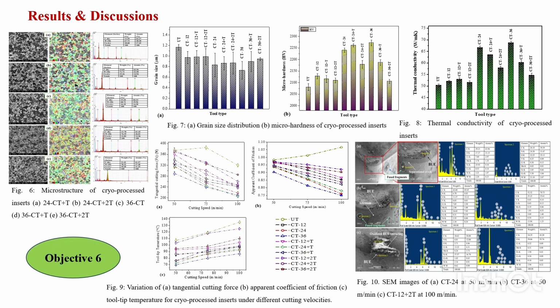Objective 6, we can see grain size distribution, micro hardness, and thermal conductivity. Higher soaking periods for the 36-hour sample might have facilitated formation of dislocation entanglements, which might have acted as nucleation sites for grain boundary formation and hence finer grain size. Higher hardness was observed with the 36-hour soaked samples, reflecting optimal carbide precipitation and grain refinement. Similarly, thermal conductivity was high due to the redistribution of free cobalt, which has increased the tungsten carbide contiguity. Hence thermal conductivity was high for this particular sample. Now here we can see from the graphs, the 36-hour soaked sample has led to favorable outcomes as well.